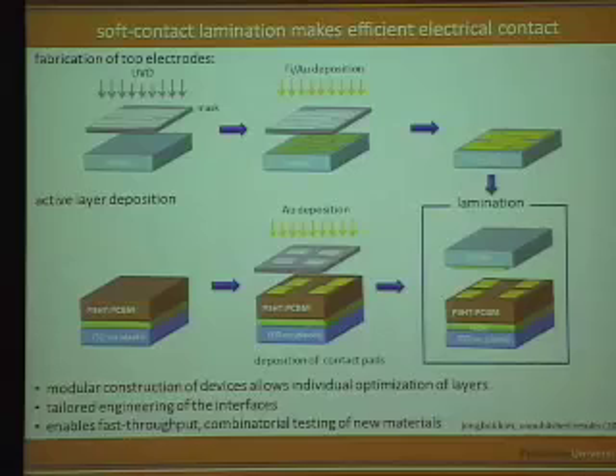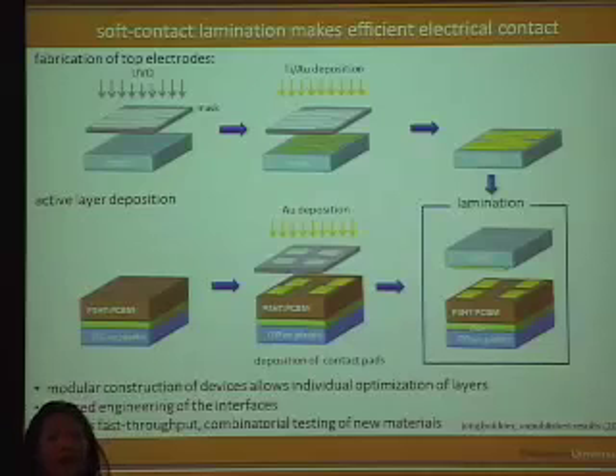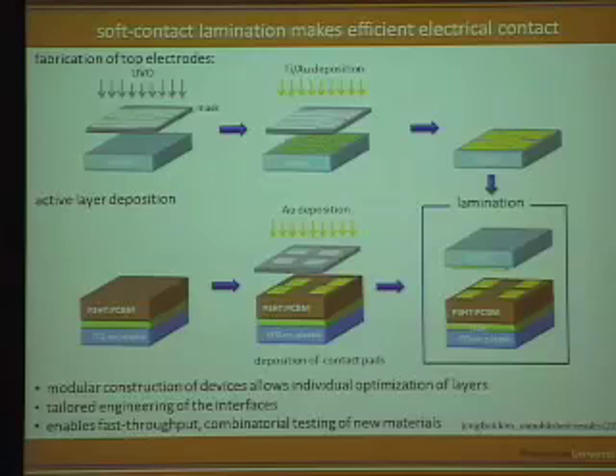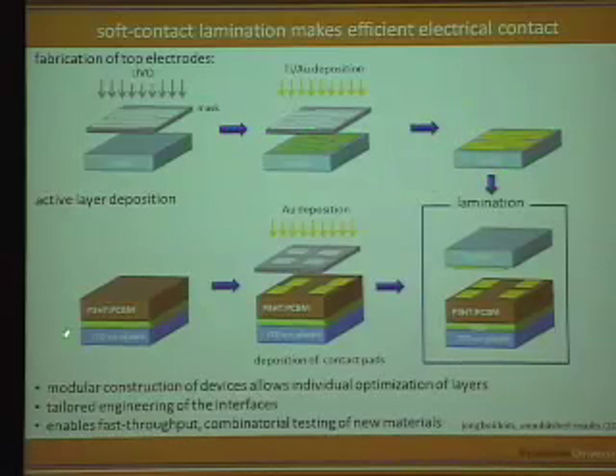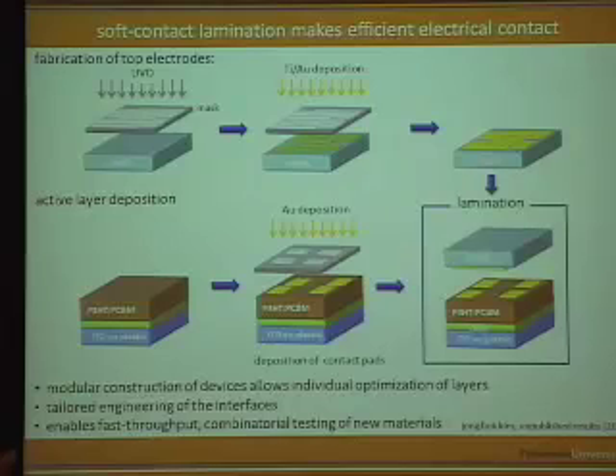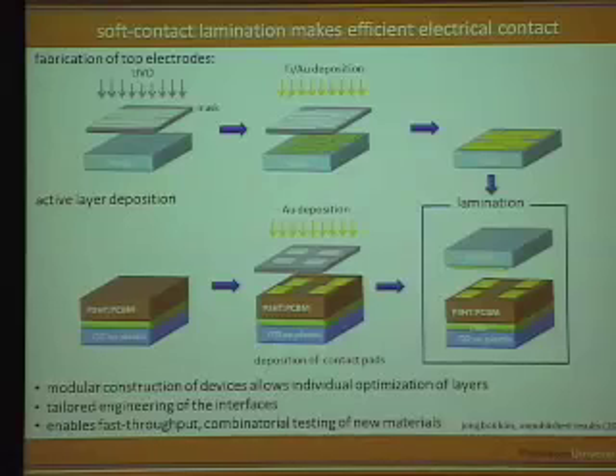So the idea here is as follows. You want to make these devices separately, okay, the different components separately. And then in one final step, you bring them together. So in this example, we've basically patterned and deposited electrodes separate from the active layer. Here we're using polydimethylsiloxane. This is silicone. This has the same chemical structure as the RTV that you use to caulk your bathtub. You can pattern and deposit your electrodes without harming the photoactive layer. And then when you're ready, you laminate to make contact. Now, there are several merits associated with this lamination procedure.